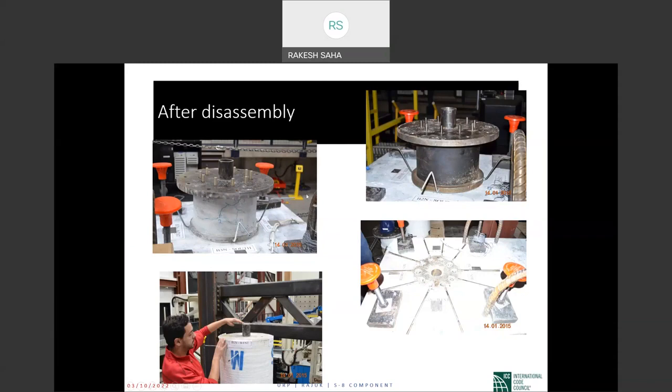In some of the other columns, we use the rubber element, absolutely no damage. The piping connection that we had up there, it's upright, no damage at all. So this one also performed as what we called capacity protected element. Now, once we remove this element, we also remove the SMA bars. So you notice these are the bars after the bridge was subjected to 6% drift.